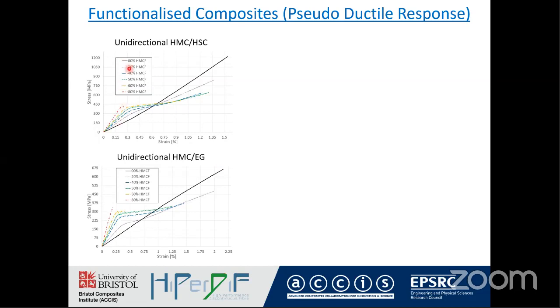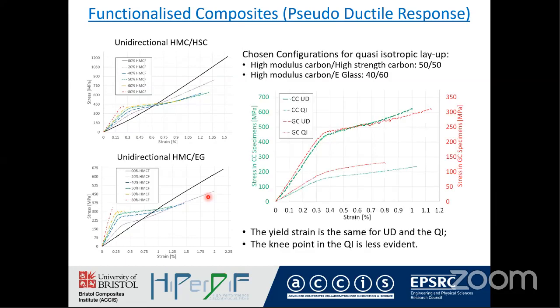And what we're seeing here is, as one starts to increase a second component, and here it's a blend of high modulus and high strength carbon, and high modulus carbon and e-glass, you can see that there's a distinct knee, a plateau that's reached in the properties before the material again begins to rise prior to final failure. So this pseudo-ductile response is also retained when you start to produce the quasi-isotropic material.